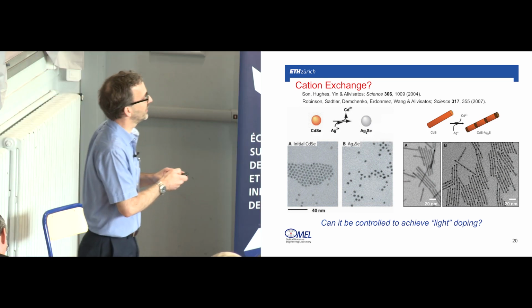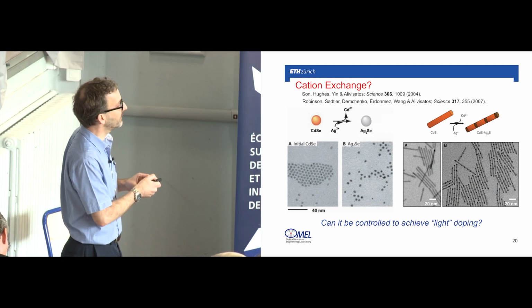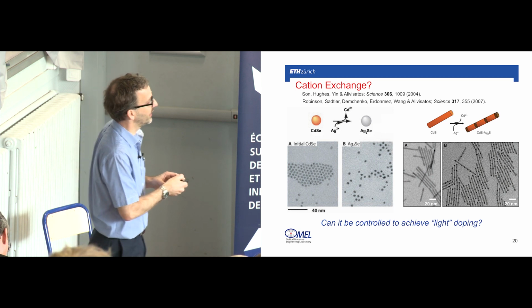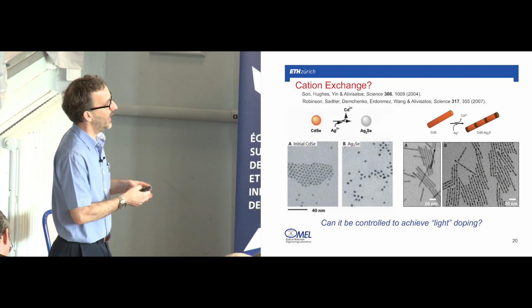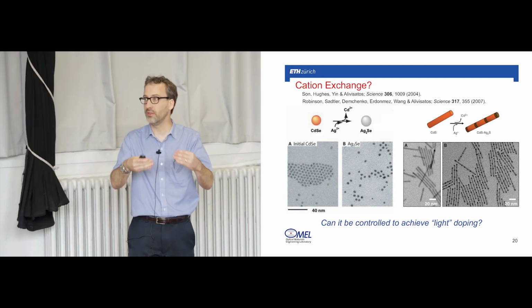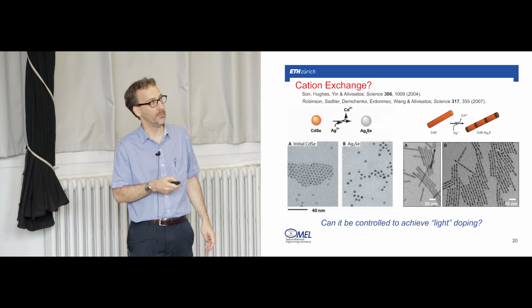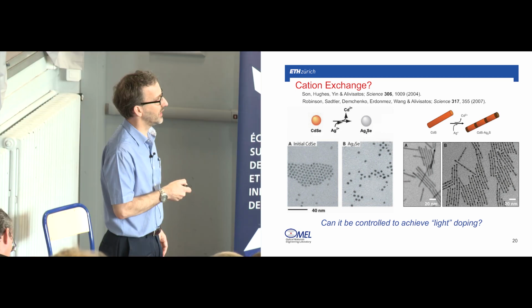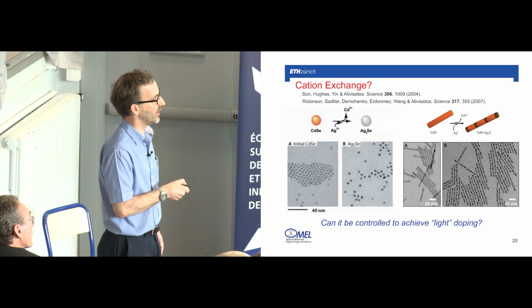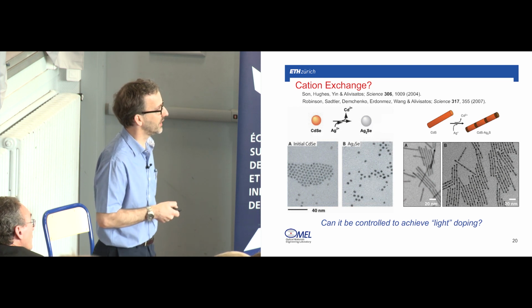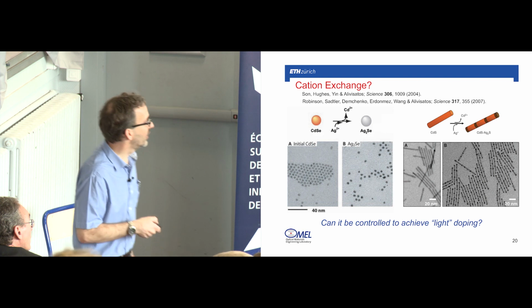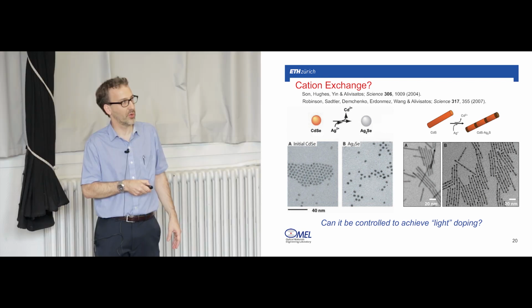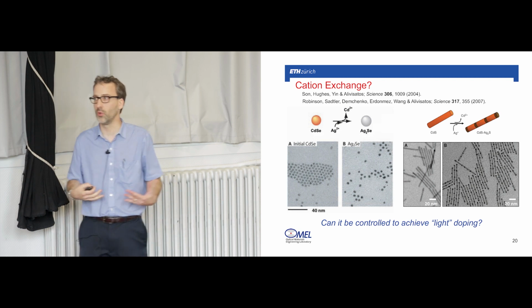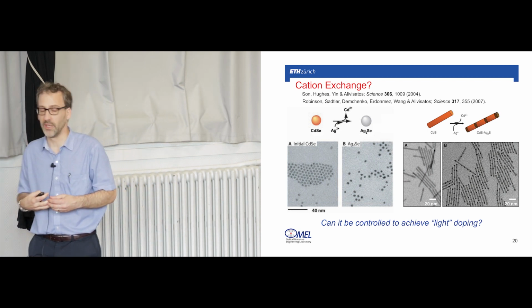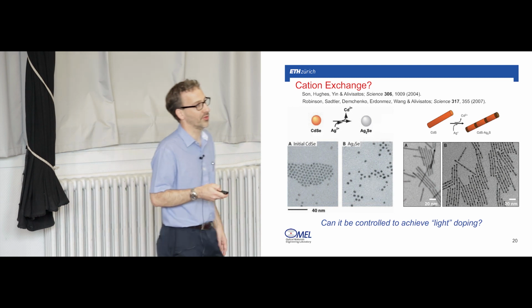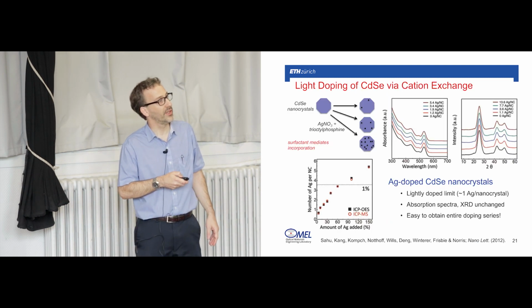And they tried to slow this down, actually for doping. Richard Robinson told me that when they were doing these experiments, they were trying to do doping. And this process was so efficient that even if they tried to stop it midstream, they just got phase segregated, in this case nanorods, where they got stripes of silver sulfide and cadmium sulfide rods. So the process was super efficient, and the question we were trying to address is, can we really slow it down enough to get to this doping limit of 1 impurity per nanocrystal? It turns out this is possible.